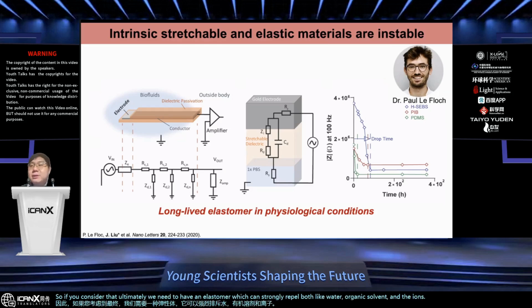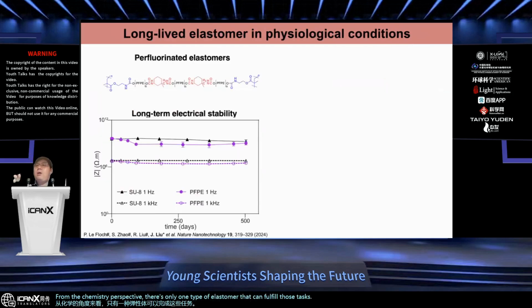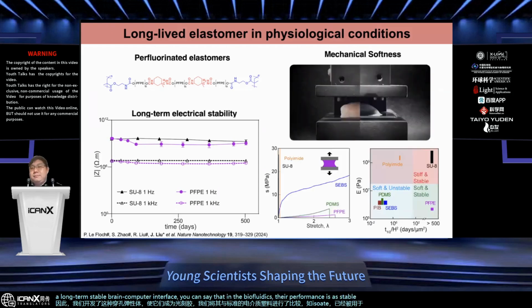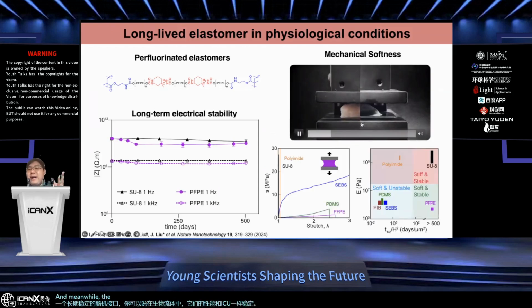From the chemistry perspective, there's only one type of elastomer that can fulfill those tasks. That is the perfluorinated elastomer. So we developed this perfluorinated elastomer and made it a photoresist. We compared it with standard dielectric plastics like SU8 that are already being used in long-term stable brain-computer interfaces. You can see that in biofluids, their performance is as stable as the SU8. And meanwhile, they can be made into very soft structures, as soft as the brain tissue.